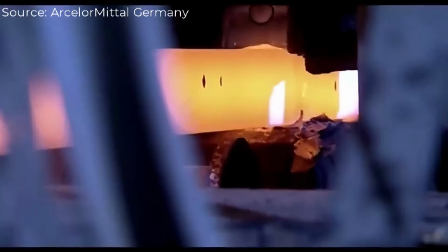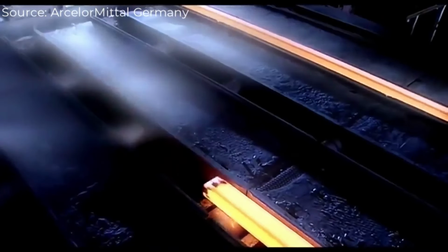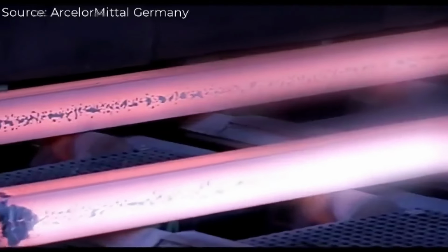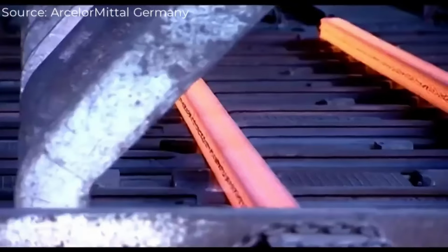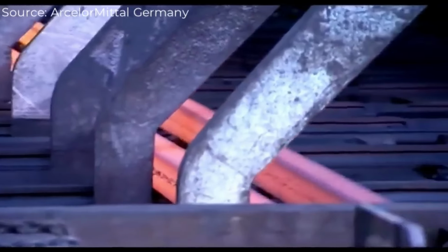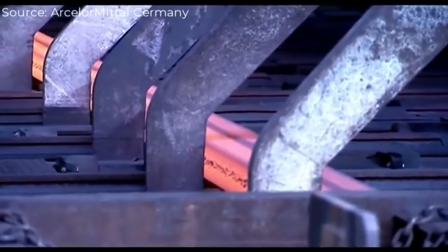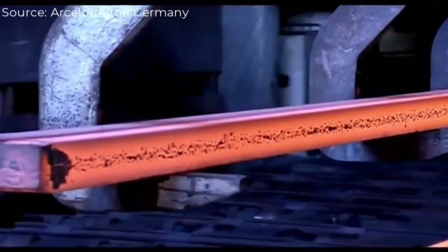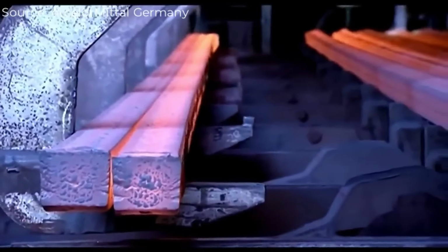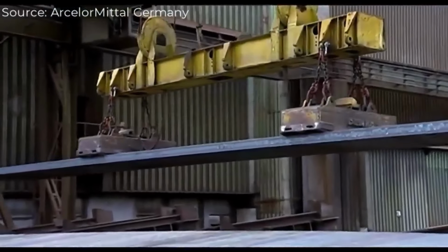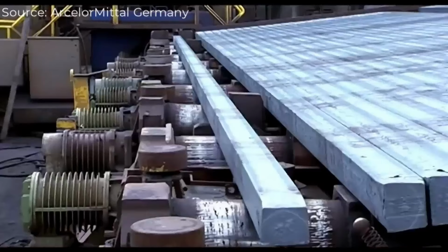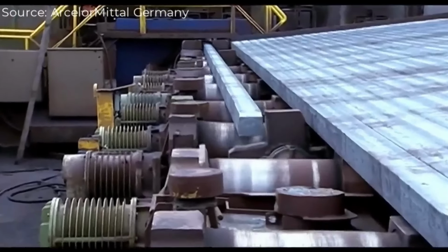The molten steel is automatically sampled to ensure quality. The steel is then poured into a continuous casting system through water-cooled copper molds, forming billets up to 16 meters long and weighing 2 tons. The billets are cooled, cut with oscillating scissors, reaching temperatures of 950 to 1100 degrees Celsius.